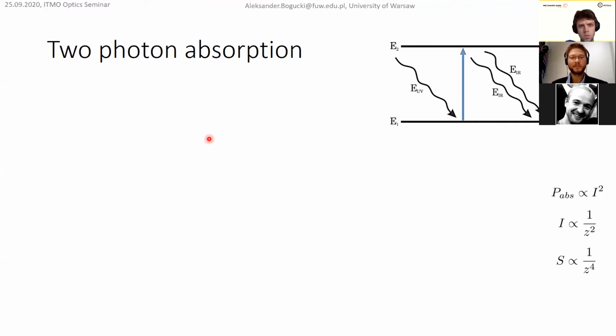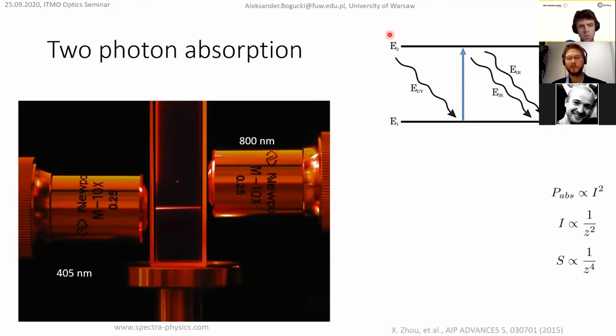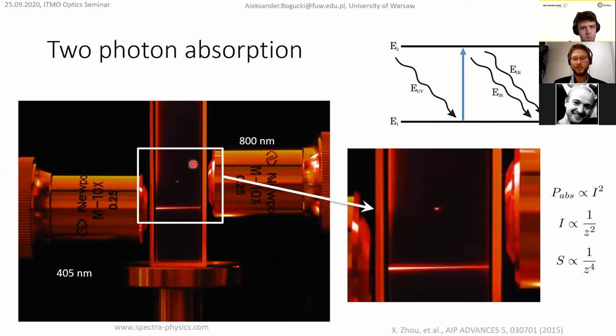So, to increase, let's say, the resolution of such printing, a process called two-photon absorption is used, which everybody probably knows. But what is quite important is how it improves the resolution. So here is the container with dye. It's, I don't remember, but probably rhodamine or another organic dye solution. And from the left side, it's excited with a 405 nanometer laser. And as you can see, this photoluminescence comes from quite a large area, even though the focus point is somewhere here. On the other hand, on the right side, it's excited with 800 nanometers, and as you can see, the only